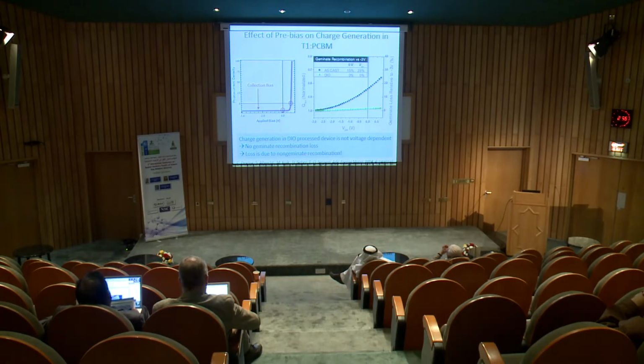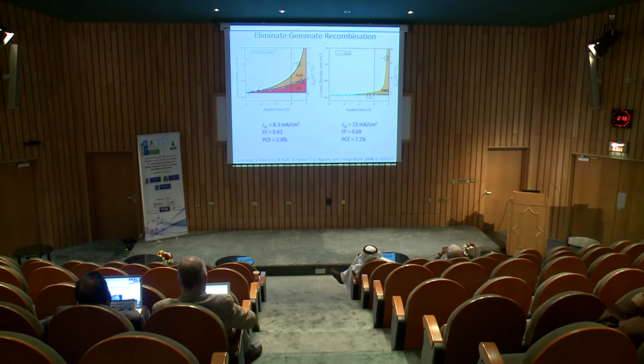So the data show us the total type of loss in our device. On the right-hand side, the DIO process device has only one type of loss, which is bimolecular recombination. On the left-hand side, the CAS device has two different types of losses: one is geminate recombination, and the second is non-geminate or bimolecular recombination. That's why you have two different loss mechanisms in the device. That's why you have lower short circuit current, lower fill factor, and therefore it impacts the device performance. You only have about 2.8% instead of 7% or so.